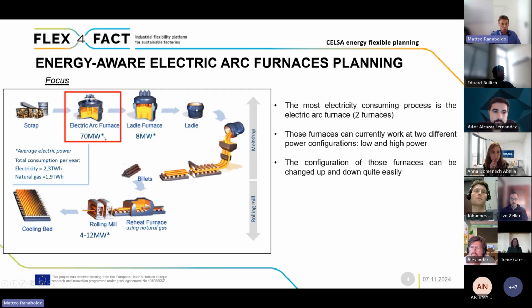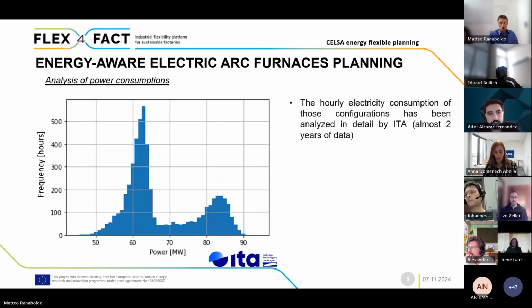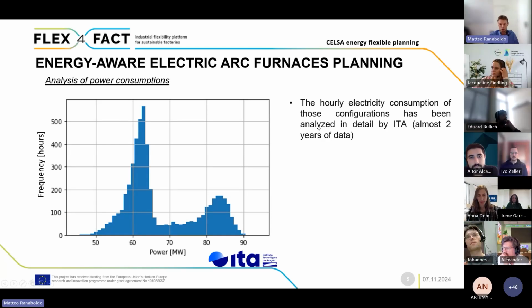Actually, there are 2 furnaces with an average consumption of 70 megawatt each. So it's 140, 150 megawatt if we sum both of them. And analyzing those processes, we see that there is certain flexibility, because those furnaces can work in 2 power configurations, low and high power, and these configuration changes can be done pretty easily by the operator and workers of the industry. So we started basically analyzing then the real consumption of those furnaces.